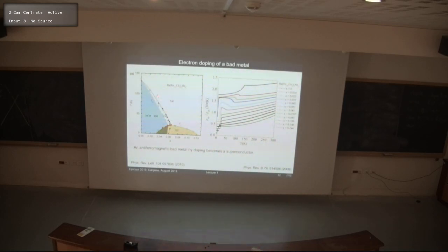So the phase diagram has this transition, and the further study, as I show you next, discovered the first transition is actually a structural transition. Then it has a magnetic transition, and once we suppress the magnetic order, we develop a dome of superconductivity with maximum TC close to about here, about 6%.